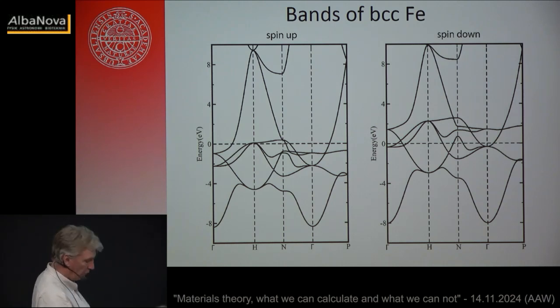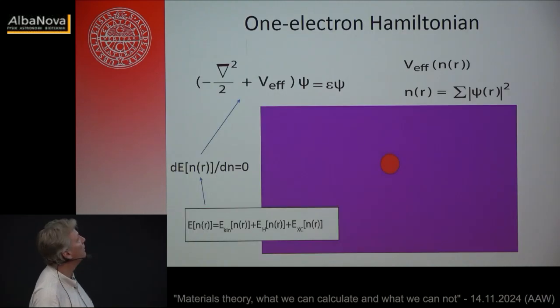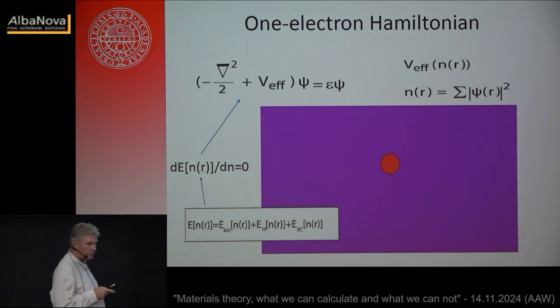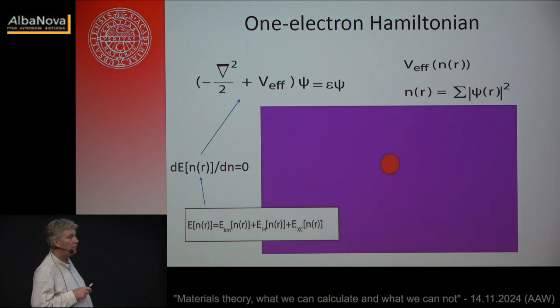No, because if you look at the total energy, the DFT functional, it has in it the kinetic energy operator, the Hartree functional, and an exchange and correlation energy. The most dominant term of this is the density to the power of 4/3. And exchange is in its nature such that it favors parallel spins, right? And this term here also understands that. Just like in Hartree-Fock theory, where you can easily see that the exchange interaction favors parallel spins, this also understands that. The reason why iron is magnetic and aluminium is not is that in aluminium, this term would also favor parallel spins of the SP band.